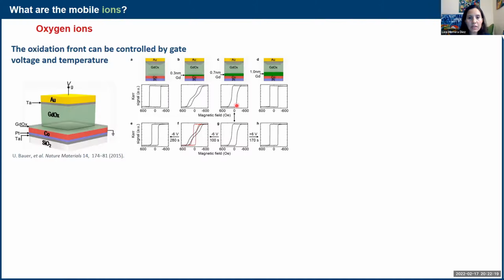And then what they did is they took this one, for example, and applied voltages to go more towards the gadolinium formation or more towards the gadolinium oxide formation. And this is what you see here. So then they could see that the voltage was equivalent to growing the layer with less gadolinium or more gadolinium. So this could really show that there was an oxidation front coming from the gadolinium oxide and going closer and closer to the cobalt layer, and that had a really large impact on the magnetic properties.